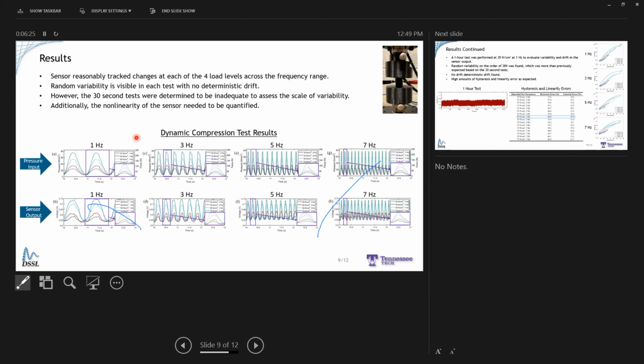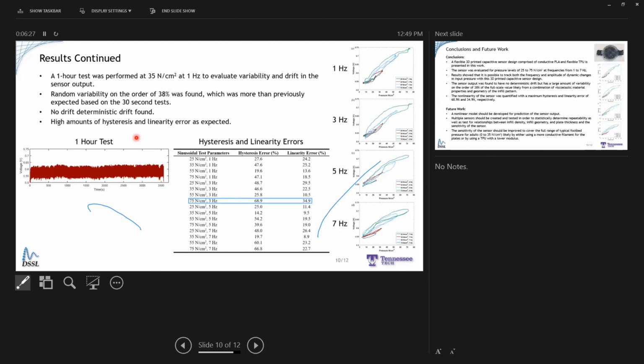So in order to do this, we ran a longer 1-hour test at 35 Newton per centimeter squared. And we found from this test that there was a larger amount of variability than we had first expected. And so we found that was on the order of 38%. And then on the positive note, though, we did find that there was no deterministic drift in our sensor system.